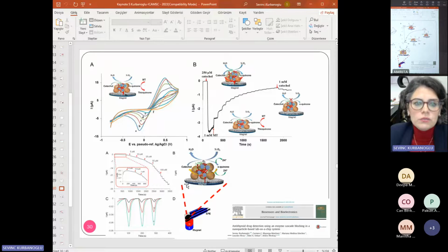So when we came to the inhibition, we tried several experiments on how we can show that inhibition. In the end, we put a very high amount of catechol, and you may see a big response. Then when we add the methimazole drug, it can inhibit directly and also indirectly. It can also chelate the coppers inside the tyrosinase enzyme, and it's also directly connected to the catechol, as I said. So when we add methimazole, we see a reverse peak, and this was really nice for us to follow the inhibition.